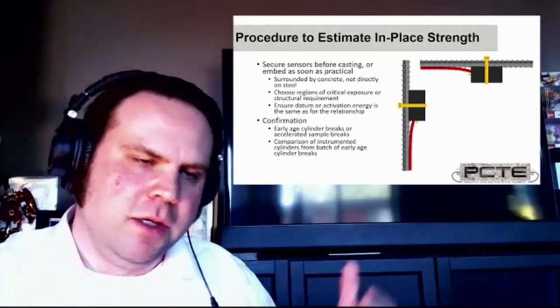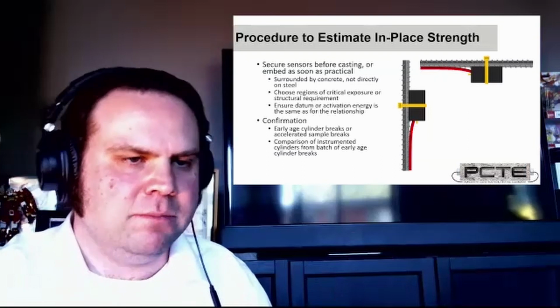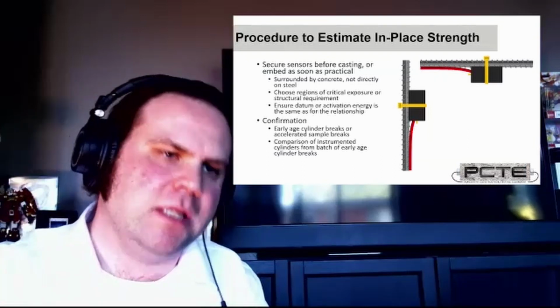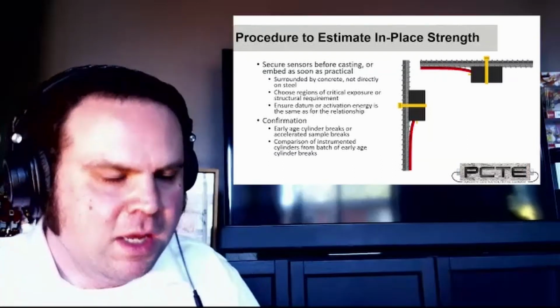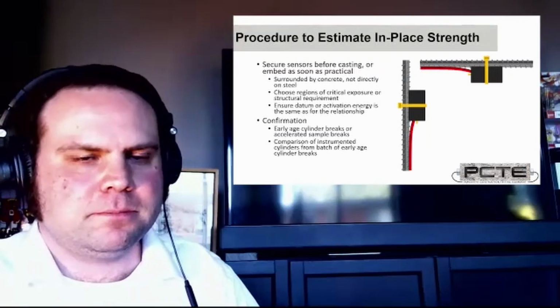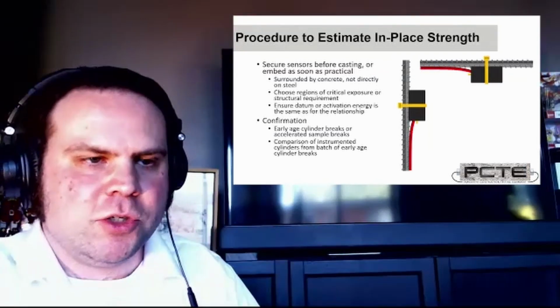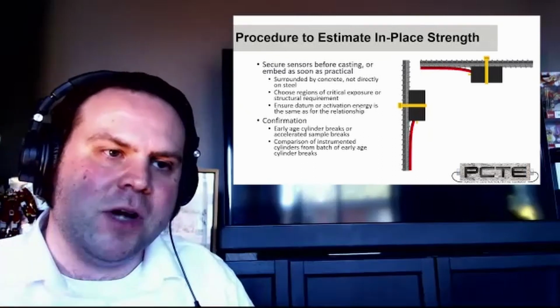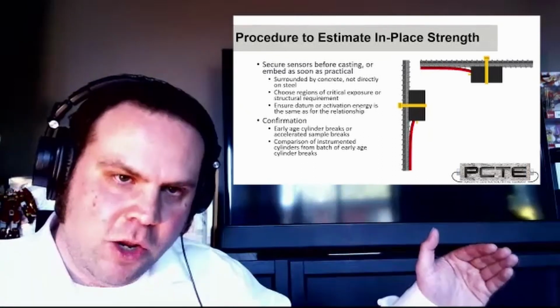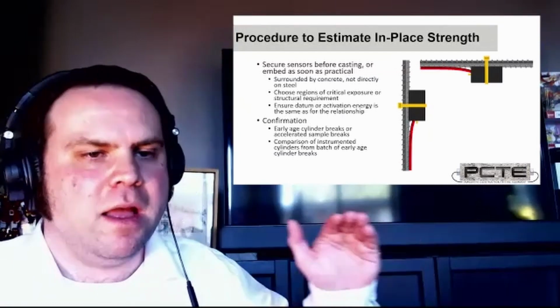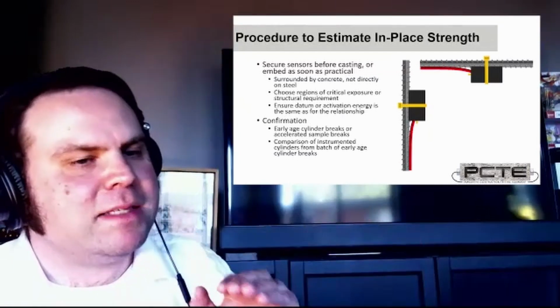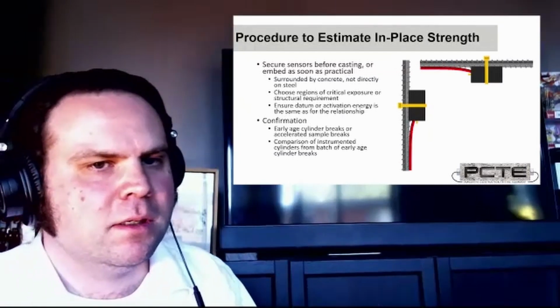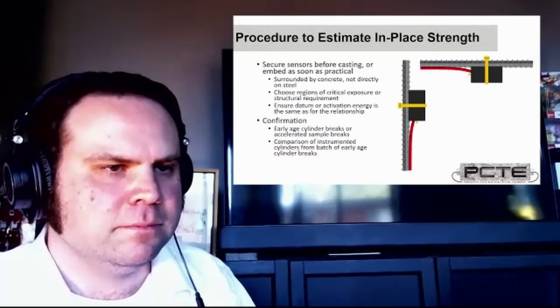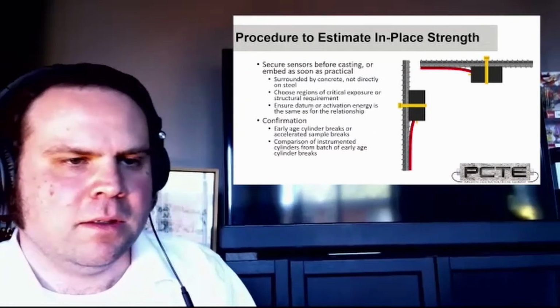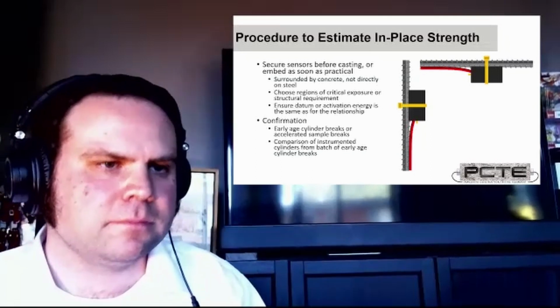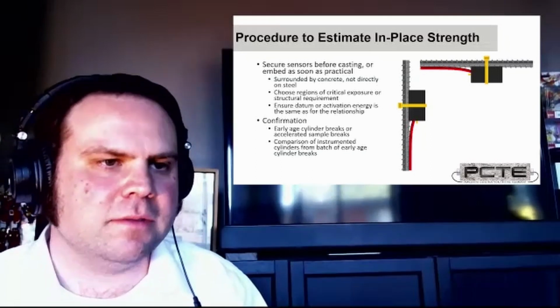It can be a confirmation cast. So maybe you put 5 cylinders in and a temperature instrumented cylinder like we did during our initial cast, and you break those. And you make sure that when you break them, the strength that they come out at matches close to the maturity index estimated strength that you're expecting them to break out. Does that make sense? Yeah, of course, it's the same as a lot of other calibration curves. You do a recheck at 2 of the main points that you're basing it on. Exactly right.